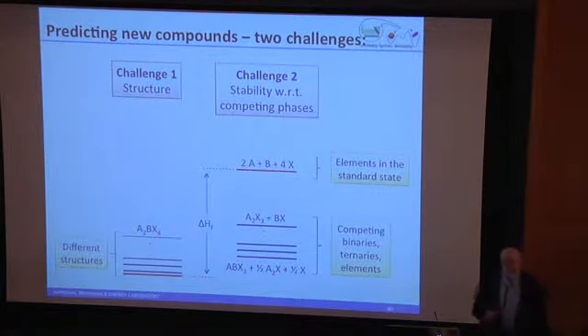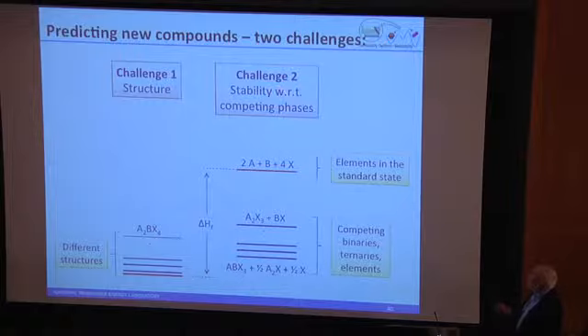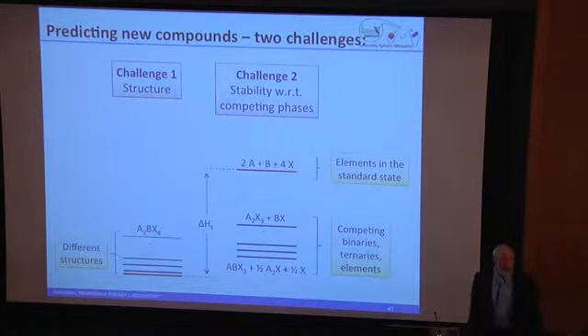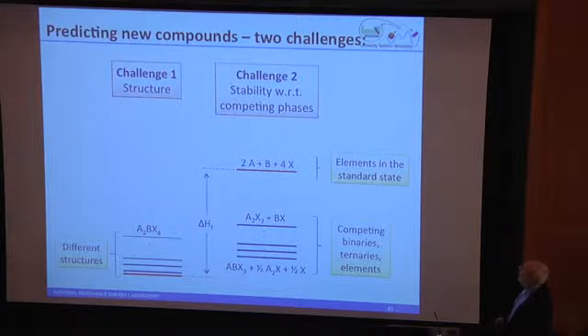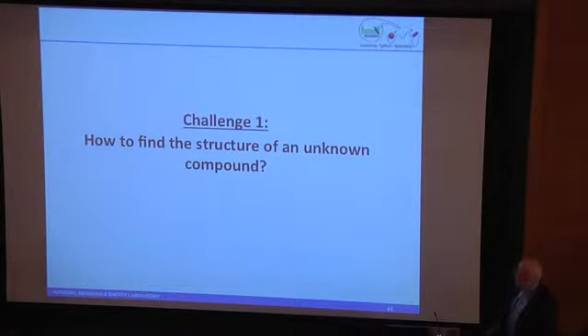And so we look across a range of essentially 40 or 50 structures that can occur. And then we have to look at stability with respect to competing phases. And then we have to look against the elements in the standard state and the other competing binaries and ternaries. And if the thing is still stable, then it probably ought to exist. We ought to be able to make it. You still have to get into price and synthesis space.